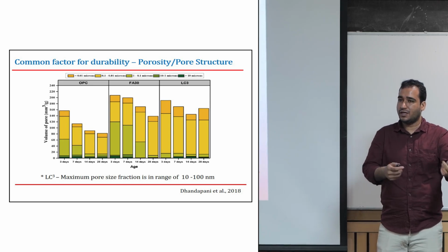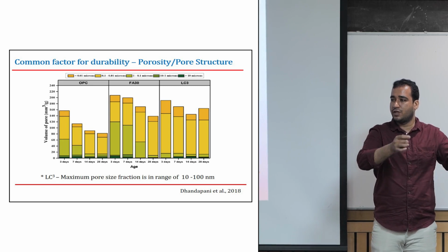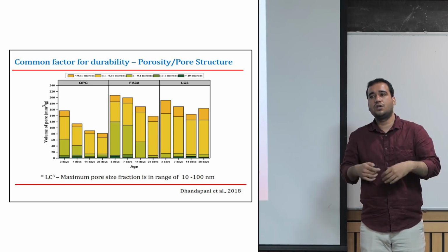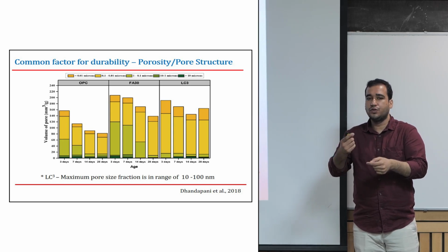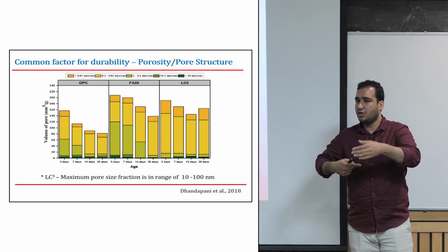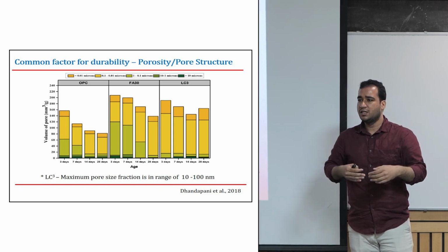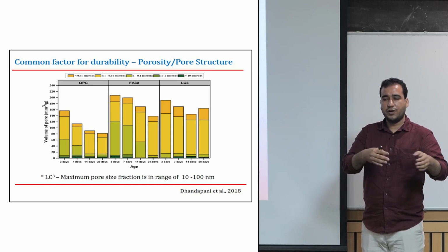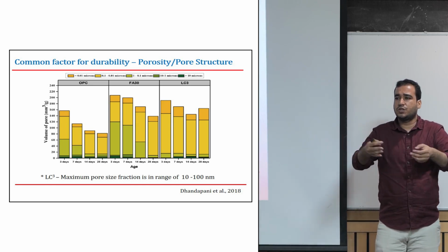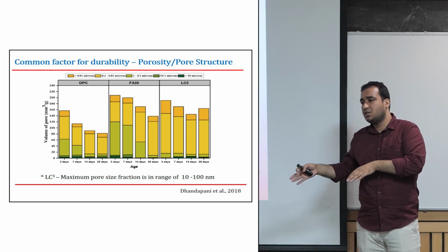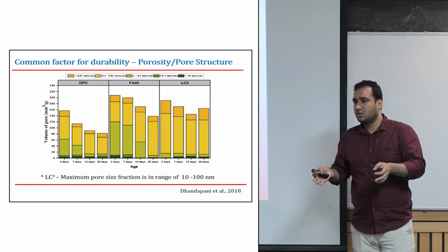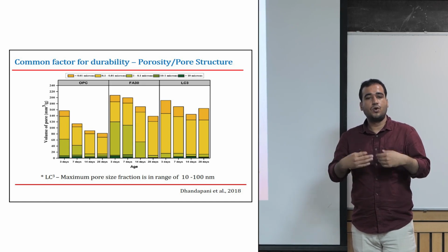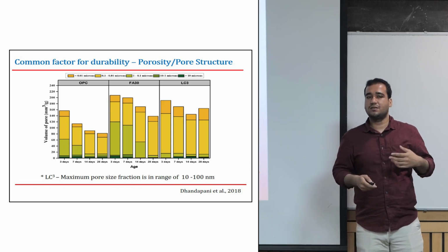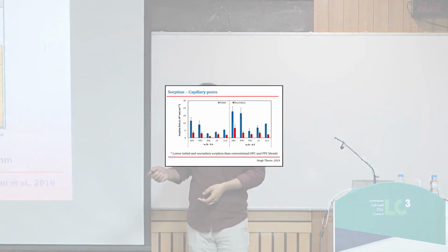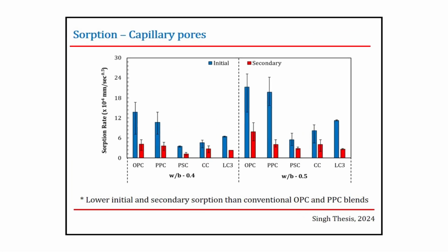It's not that just because one property gives me high resistivity, it's durable for everything. No, it's not like that. If it gives me high porosity, it's not durable. No, it's not like that. When you do these kinds of things, it's better to compare with the same kind of composition. If you're looking at OPC at 0.4, 0.5, 0.6, then it's well and good. You can compare freely because whatever is there in porosity will be reflected in the pore size distribution also, because the blend composition is the same. But when you change the composition, would the things remain the same? No, they don't. So when you are talking about different blends, I would say look at more than just one property, because this one property can be misleading. Now let's see the effect of this pore refinement and how it happens.